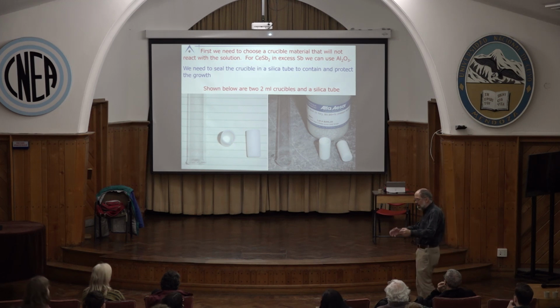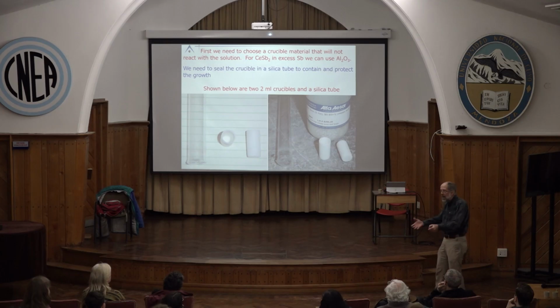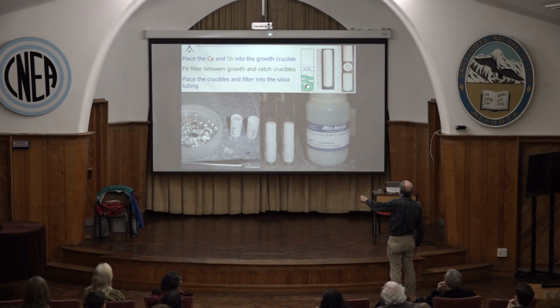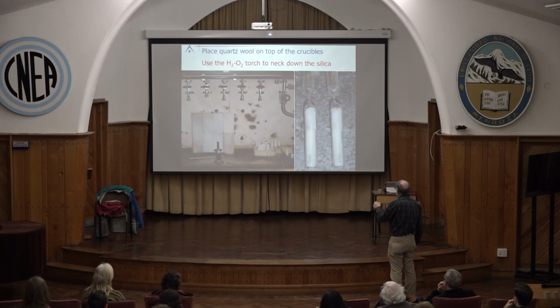I use a hydrogen-oxygen blowtorch. I get this somewhere around the order of 2,000 degrees Celsius. I melt it, I flatten it, yay. Good. Nice. Now, what do? Well, I fill the bottom crucible with a lot of antimony, a little cerium. I put this filter, a fritted disc, in here. I seal these in, I put these into these tubes. And I put a bunch of quartz wool on top, because that's a cushion. I'll explain the cushion in a minute.